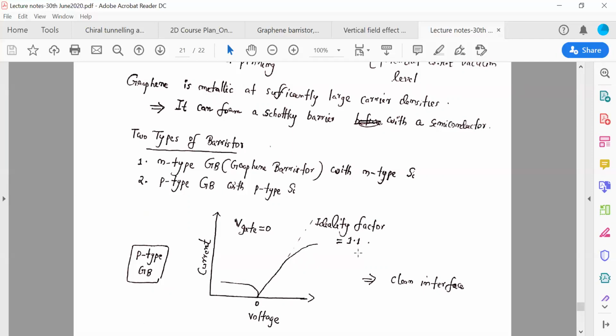In these experiments, they have made 2000 devices on a 6-inch wafer. And they found this ideality factor actually varies from 1.1 to almost 4. So if you get close to 1, that means this is the best quality. The interface is very clean. This is the way typically people check the quality of the Schottky barrier, Schottky junction. So at low voltage, you should get this ideality factor as 1. All right. So in this example, the gate voltage is 0. So there is no gate voltage. We only have a typical Schottky barrier, the semiconductor metal Schottky barrier without tuning the barrier height. So your gate voltage is 0. And from this I can show you something here.